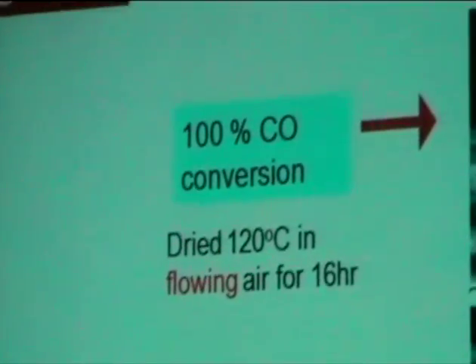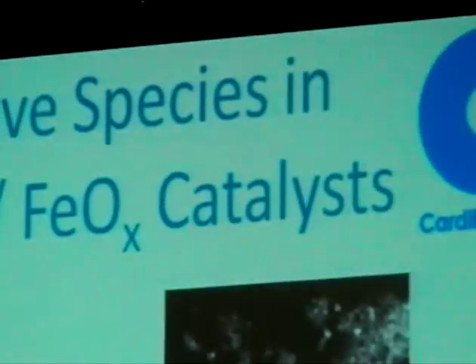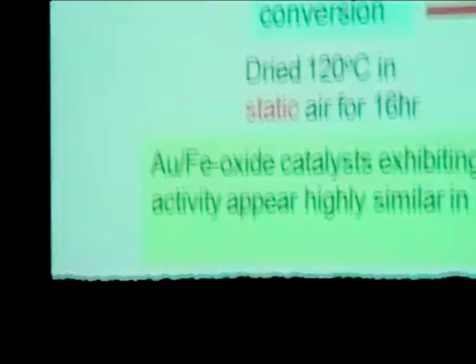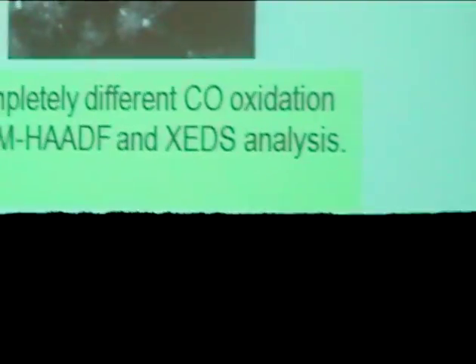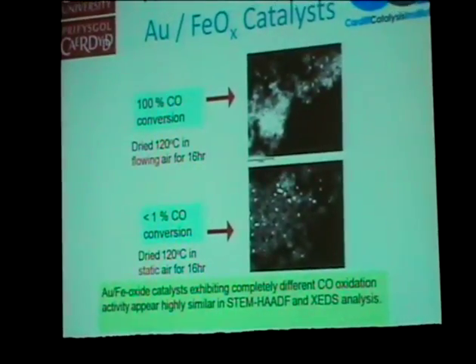This led Professor Hutchings to start thinking about what could be the active site in these gold and iron oxide catalysts. We prepared a number of catalysts by co-precipitation of iron nitrate and tetrachloroauric acid with sodium carbonate. These catalysts were then dried in different methods. The first catalyst was dried in flowing air at 120 degrees C for 16 hours, and this turned out to be an extremely active catalyst for CO oxidation.